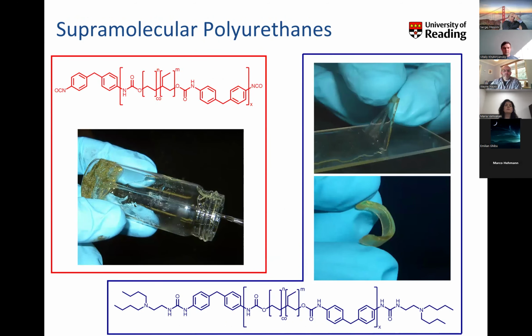Now, the properties of these materials, from the pre-polymer to the desired polyurethane, are quite dramatic. The pre-polymers tend to be quite thick, viscous oils, which aren't always the easiest to process, if I'm being honest. But once you've end capped them, you produce materials which are elastomeric in character. Shown here is just one of the derivatives we've made, which has two urea end groups and alkyl amine chain ends. And that material is a really nice adhesive.